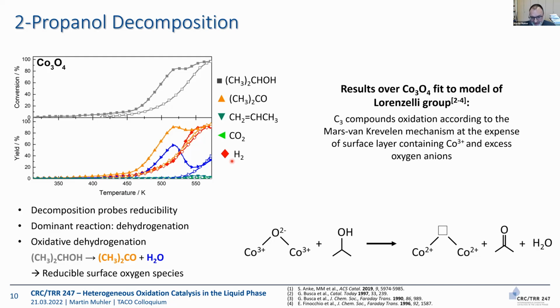It's now pretty simple to summarize these observations. When you think about what is chemically needed to transform 2-propanol to acetone and water, then you inevitably arrive at such a simple cartoon. You need 2 cobalt-3+ ions to accept the 2 electrons and a nucleophilic oxygen anion. So nucleophilic meaning having a lot of negative charge, acting as a base. Here we have to break the OH bond and the CH bond, and then this oxygen ends up in water, and what is left is then an oxygen vacancy and 2 reduced cobalt ions.